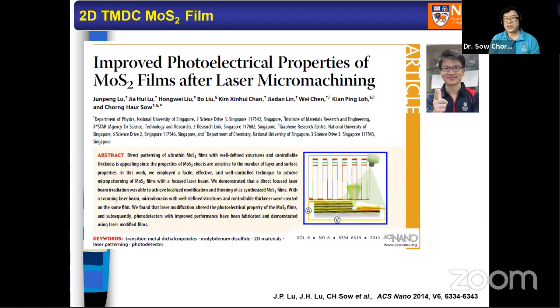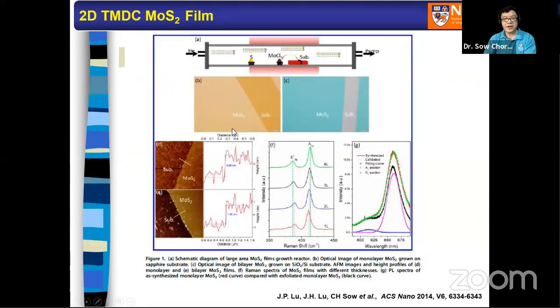So we know that MoS2, if you have more than one layer, you are having an indirect band gap material. But when you tune it down to one layer, it becomes a direct band gap material with very strong emissions of fluorescence color. So now what we did, we take CVD grown MoS2 film with, let's say, a few layers. We can use a laser beam now to locally trim the local region from a few layers down to a monolayer, of course, very carefully. And this allows us to achieve a junction whereby on the left side is four layers, right side is one layer.